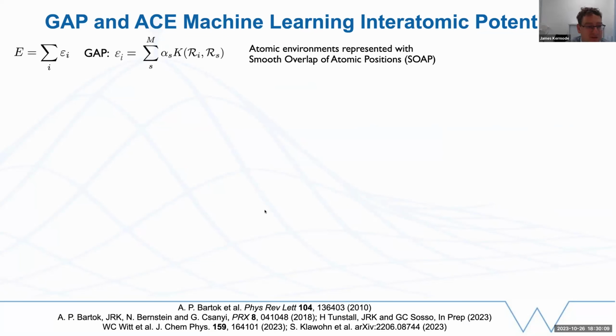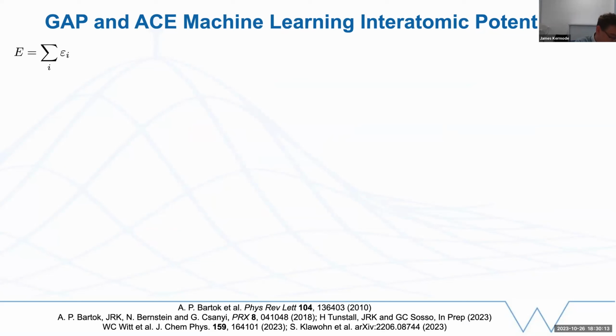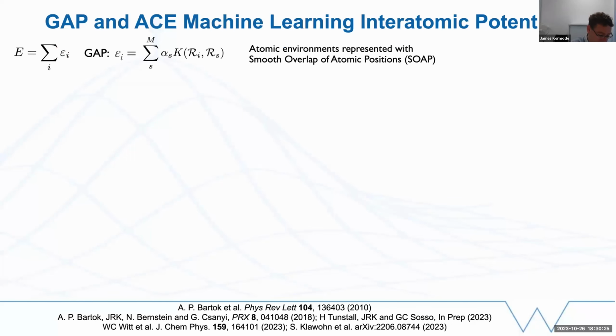The Gaussian approximation potential, but all of these potentials are similar in that the common assumption that we make is that we can decompose the total energy into a sum over contributions from individual atomic sites. In GAP, the way that we do that is in particular by comparing the atom of interest, where we'd like to make a prediction, with a set of reference atomic environments through some kind of covariance kernel, and then we have some weights here that we've determined from our training set, essentially. So that's the Gaussian approximation potential, or GAP, approach.